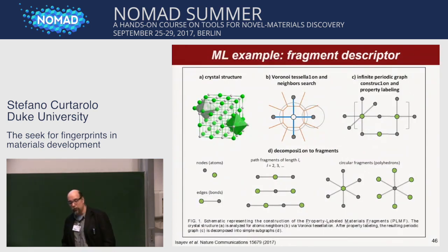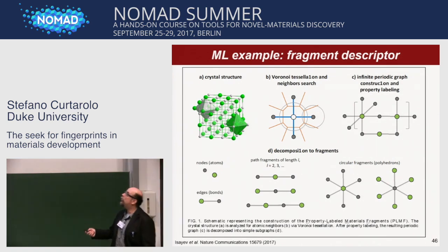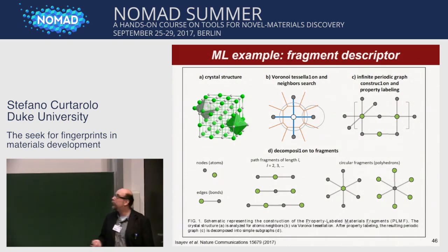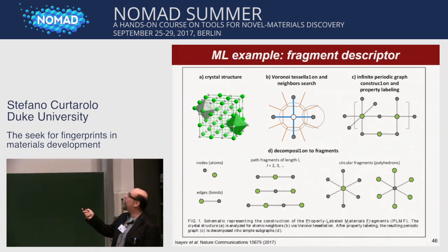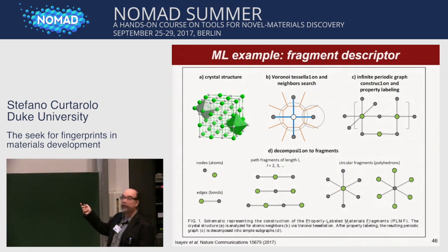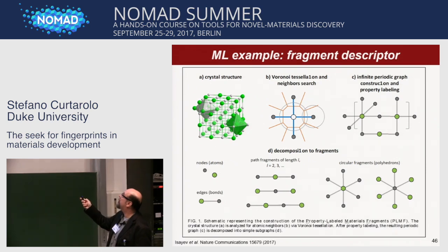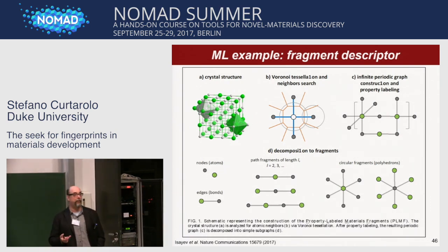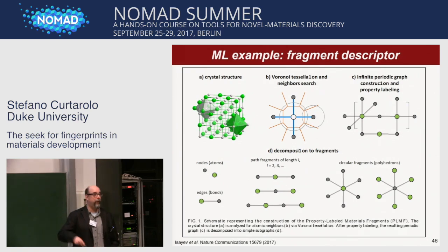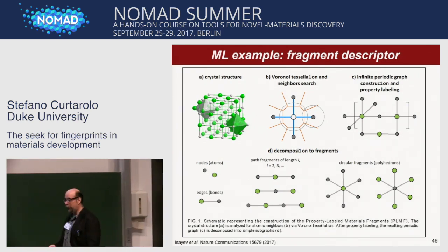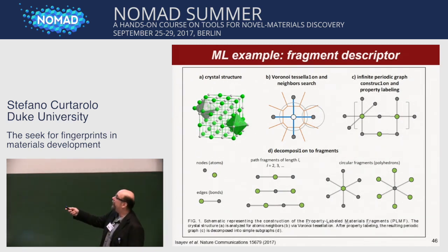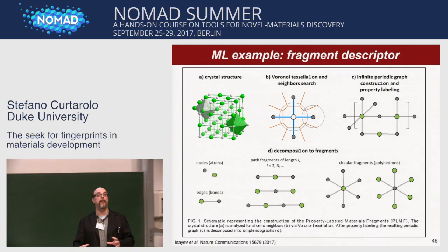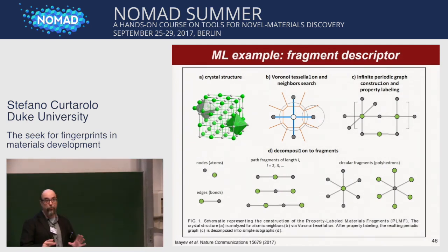For electronics and for energies, we chose what we call the universal fingerprints, which are information about the crystal structure and about the topology of the voids, or the topology of the connectivity. Suppose that this is a unit cell, so the green goes to the green, it needs to go right and left, then up and down. We code all this information in the same way that people who develop drugs try to figure out all the directions they need to go to find the chemical properties they want. And also in terms of nodes, not on connectivity, but in terms of how compact the cluster is or not. So those are our descriptors, and we train the model.